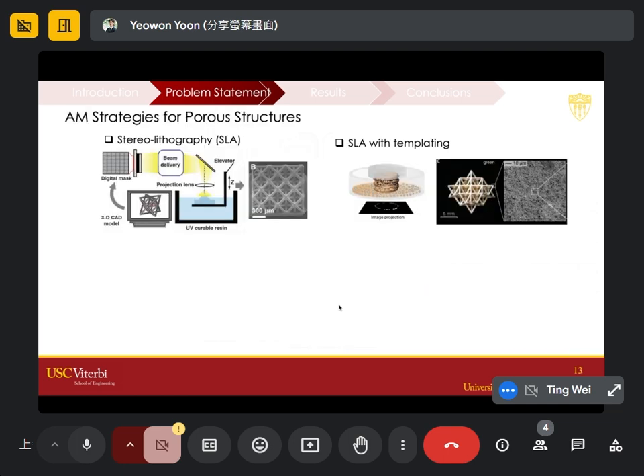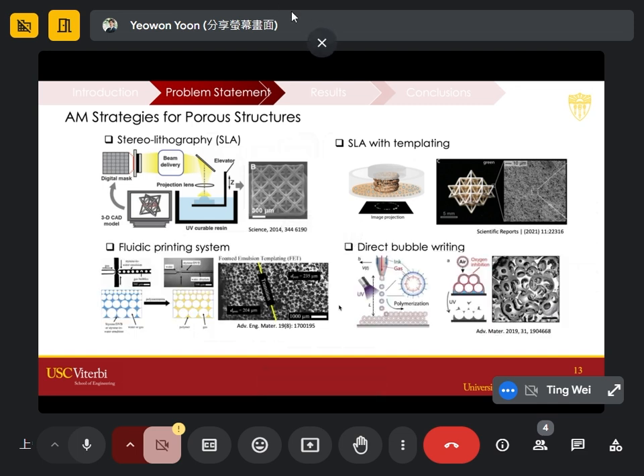Yeah, so there are already existing methods to do this using AM or 3D printing. With stereolithography or VPP, you can just print pores as is in the 3D CAD system. Another method is using SLA with templating. Templating means you have sacrificial droplets inside, then later these droplets will be removed from the structure. A more recent approach is a fluidic printing system. You basically have a two liquid junction to create an emulsion of the droplets, and then these droplets will later be removed. And more recently, we have a direct bubble writing system.